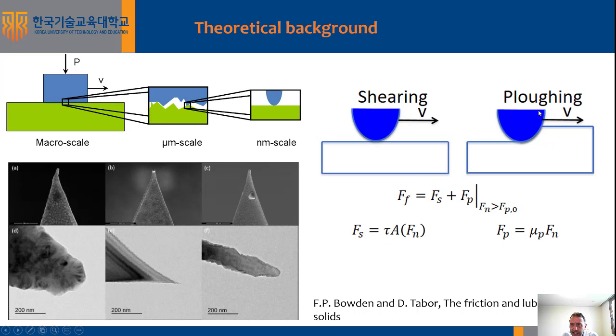And now in the case of plowing, we consider that an asperity is pressed onto a surface at some threshold load, so that it starts penetrating inside the counter body, and upon sliding it will essentially plow inside the counter body and push some material ahead of it. In that case, the plowing force can be described as the product of a plowing coefficient times a normal force.